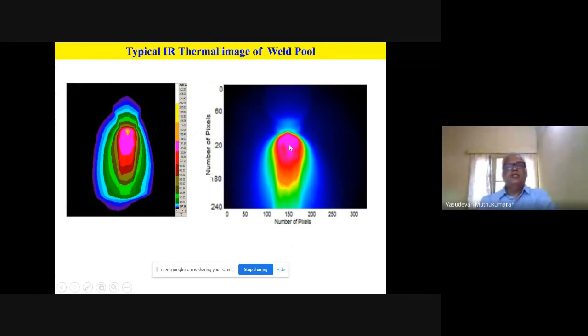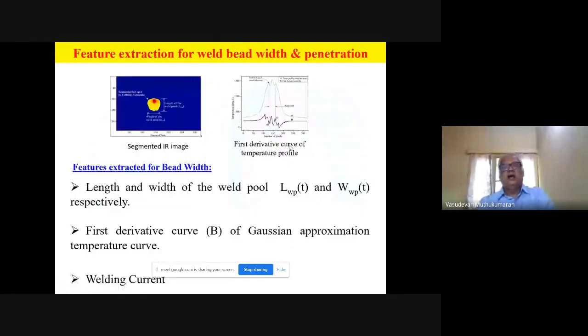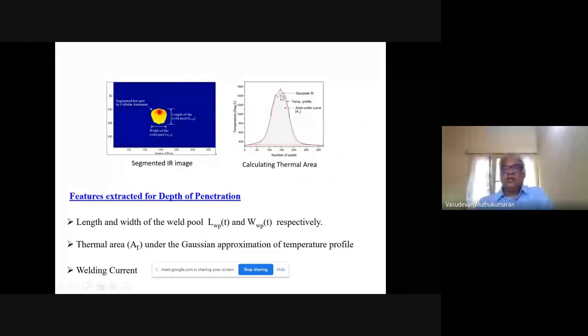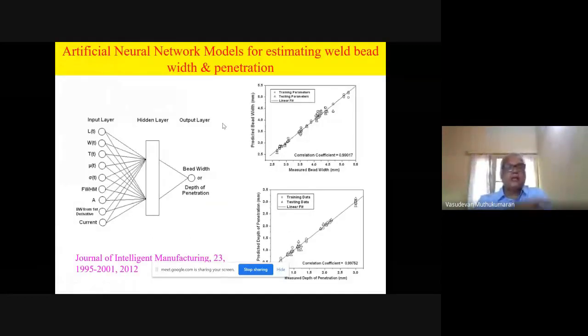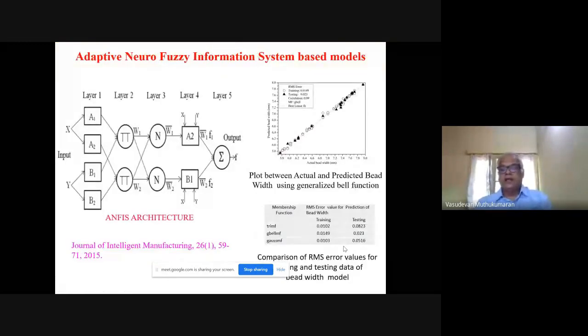This we used for feature extraction and image detection techniques. We could get features like the length and width of the weld pool, and the first derivative from the temperature profile curves to correlate with the weld width and depth of penetration. For depth of penetration, we use the area under the thermal profile to correlate with the depth of penetration. Then we developed neural network based models using these image features and the parameters as inputs, to correlate with the depth of penetration. See the measured weld width and the predicted weld width. See the very good correlation for both depth of penetration and width, based on the neural network model. Then we developed ANFIS-based models as well to get more accuracy.